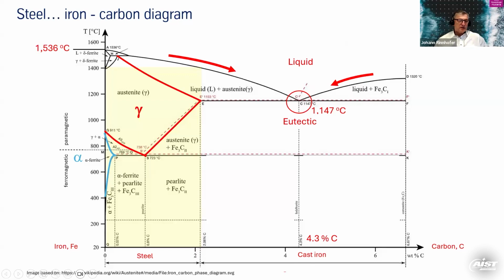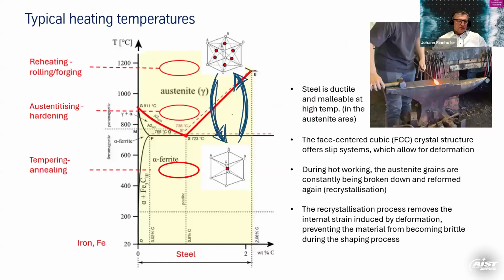So this is why this is important. Typical heating temperatures are for reheating in the area of 1200 degrees, because steel is malleable at this high temperature in the austenite area, basically. This is because we have a face-centered cubic crystal structure which offers slip systems. So you cannot shape and form steel in a cold condition like you can at these high temperatures, as we all know from the forges. I'm actually a member of the Blacksmith Association of Western Australia. This is why I show the picture here on the right upper corner.